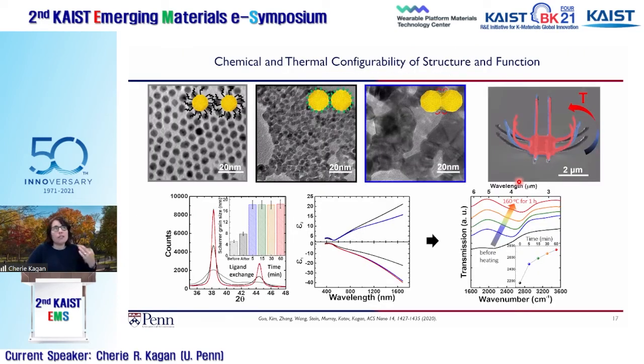And so I'll just give you a sense that, just like when we do the ligand exchange, we bring these particles closer together. If you further anneal this, these grains really grow to form polycrystalline materials. And so if you subsequently further anneal these materials, you'll get greater fusion. And it doesn't change the optical properties very much if you look at the real and imaginary part of the dielectric function. It stops evolving quite as much, but it creates much greater misfit strain. And so you can see here that as you anneal a structure, you can control how much the arms would curve.